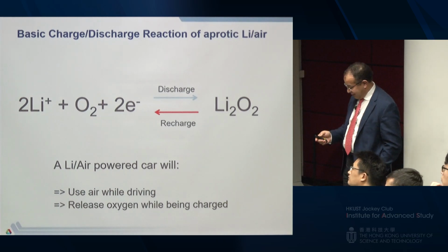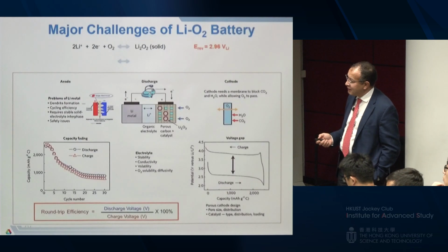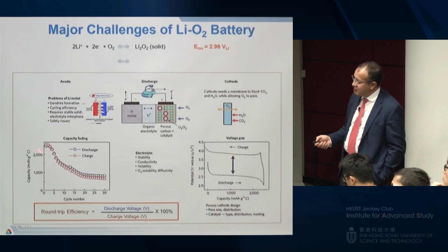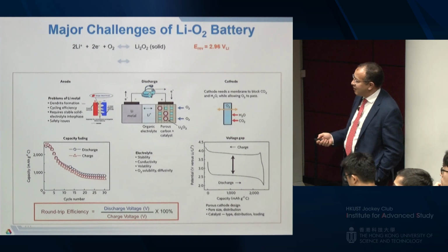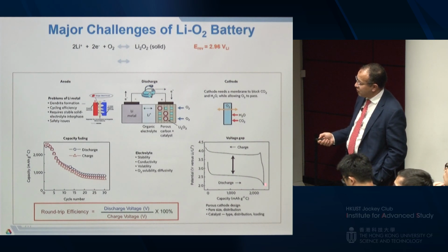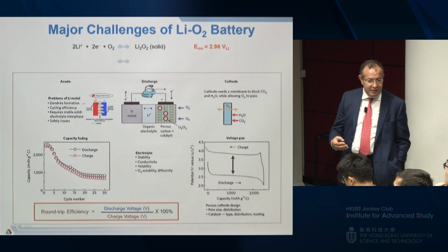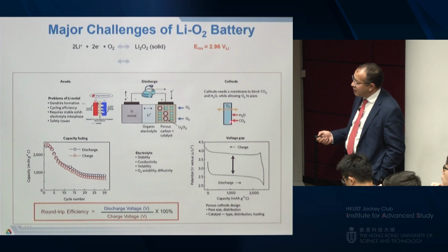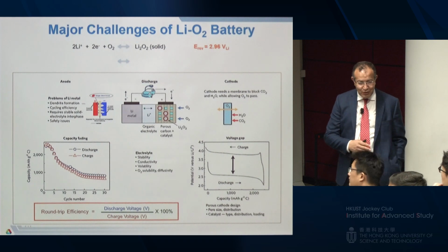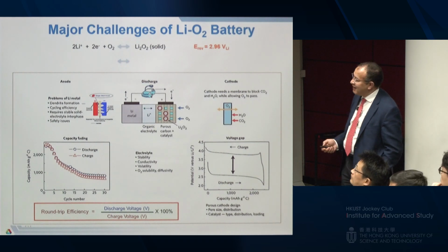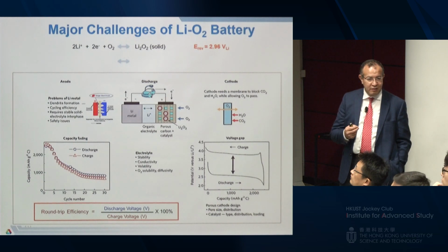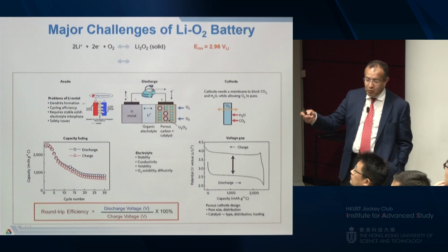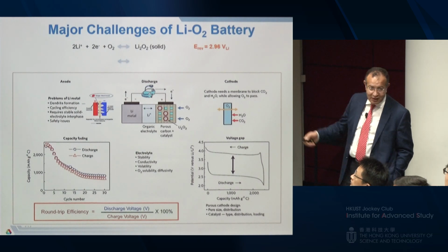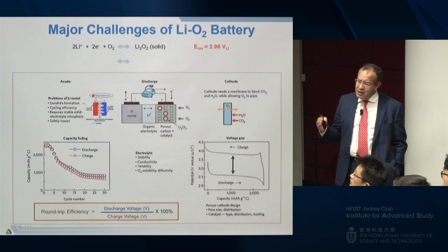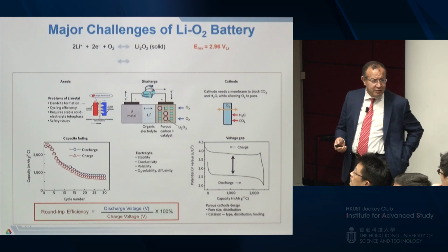But there are so many problems with this system. You can see the polarization is huge. You basically cycle for 10 times, it dies. One of the reasons is that the discharge product, which is a peroxide, is very corrosive. It attacks the electrolyte and destroys it. You have oxygen crossover that reacts with the lithium metal, forms lithium hydroxide, so you completely lose your anode. So that's why it dies quickly. The peroxide does not dissolve in the electrolyte, so it stays and it clogs the pores of the cathode, and then oxygen has difficulty moving in, so the feed becomes very low. These are just a few examples. You still have lithium dendrite from lithium metal and so on.